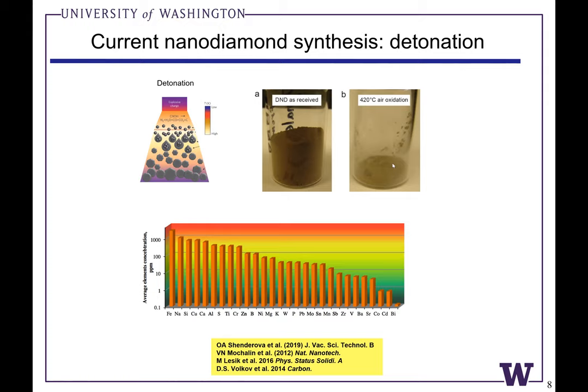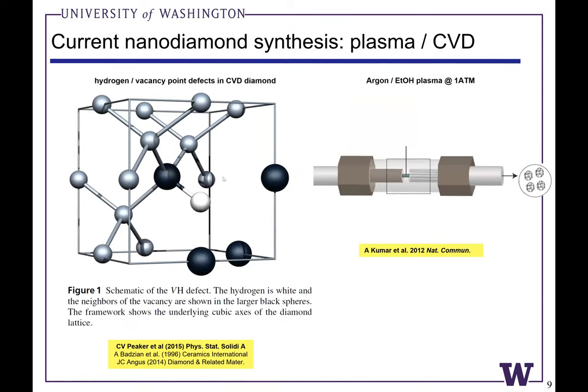Air oxidation can be used to get rid of some of the soot, and you can oxidize a lot of the metals, but it requires a lot of processing to purify the detonation material for these very sensitive quantum type applications. There's also been a lot of work recently in plasma growth of diamonds. So there are some really nice papers showing the growth of diamond using a methane-based plasma. But one challenge in plasma growth is you often get hydrogen point defects in diamond. And this can quench the optical luminescence of the negatively charged nitrogen vacancy center. So we're looking for methods that can avoid metallic impurities and also avoid hydrogen.